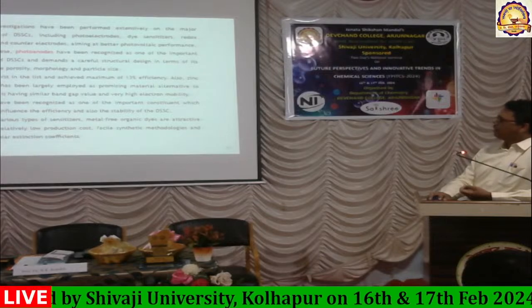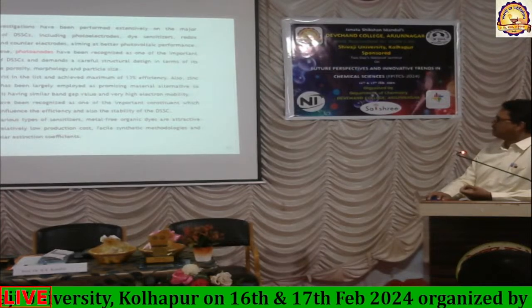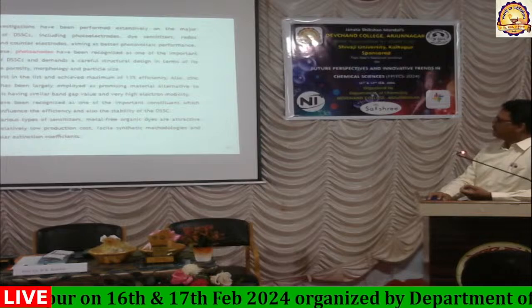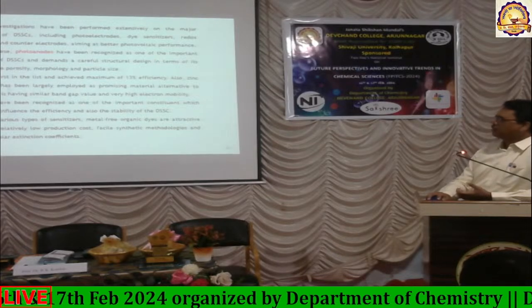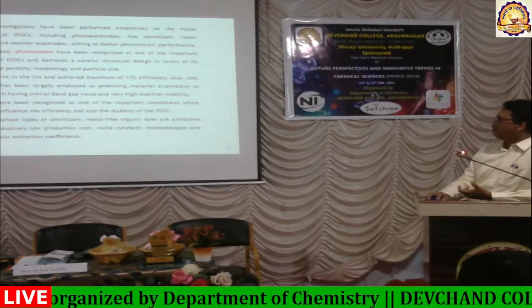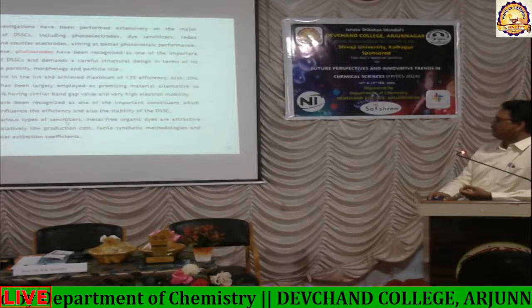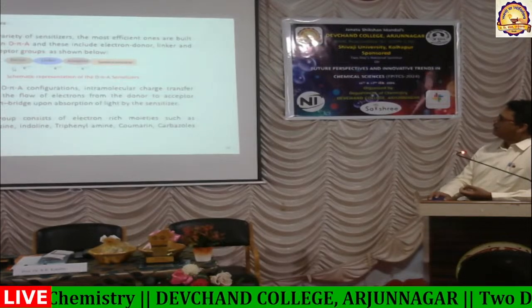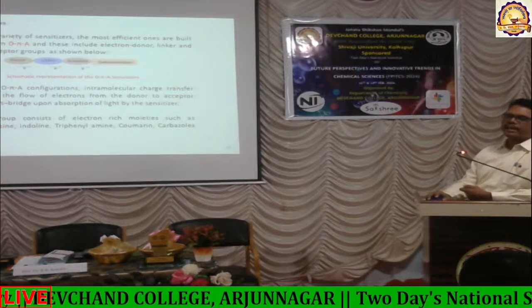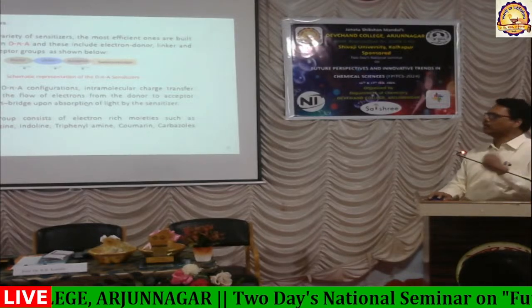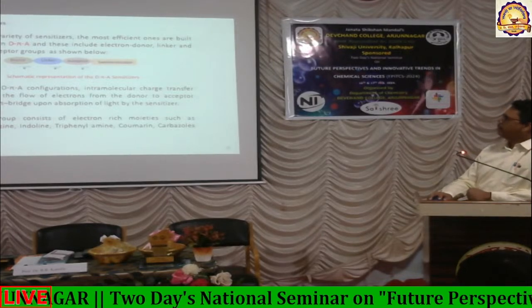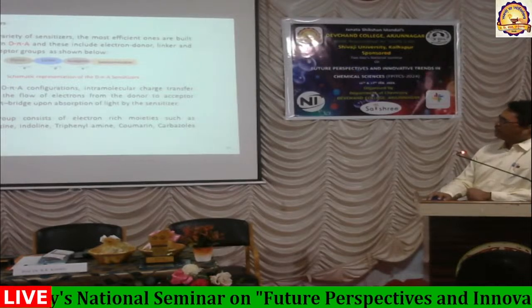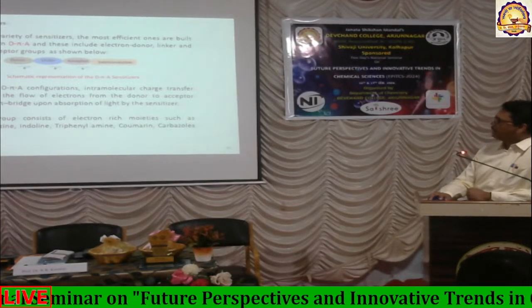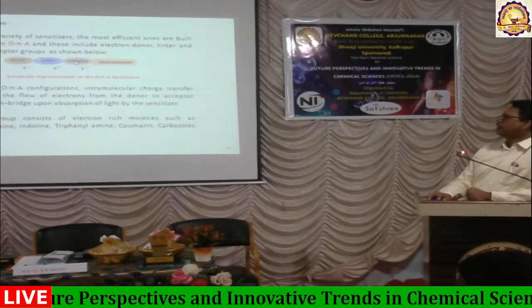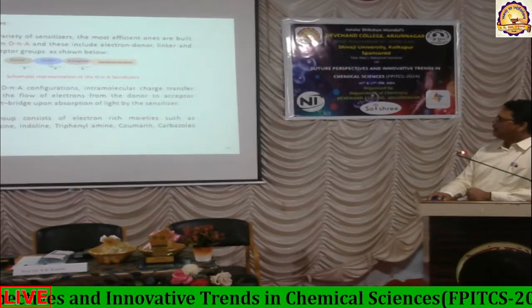And TiO2 is one such semiconductor, and even zinc oxide, as I told you earlier, can be a very good semiconductor. And there is a property required for the sensitizer also. Sensitizer means it is an organic molecule which has got a D-pi-A structure, means there must be a donor, there must be a pi linker, and there must be an acceptor. Okay. Donor, linker, and acceptor.